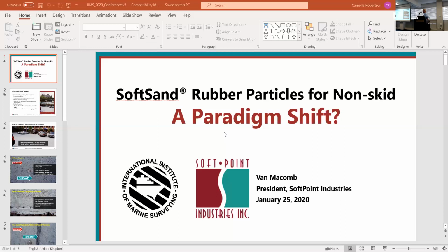That's step number one to making a good composite structure, which is how we view non-skid coatings. And then the second thing, you have to have a modulus match between the coating and the particle. You can have a rigid matrix like an epoxy or a concrete, and you use a rigid particle or aggregate. If you're using polyurethane coatings, which is what most of these guys are using on their boats today, it really calls for a flexible elastomeric particle. So that's the way we formulated this problem. And these next few slides, I'm just going to show you how we sort of prove this out over time with this particular coating system.